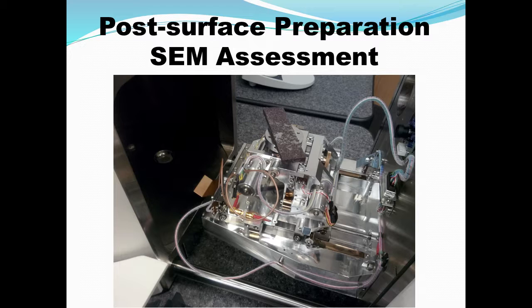I just wanted to say one thing here: time in the scanning electron microscope takes a lot of time, and we can't do 100 samples on every square centimeter of the surface. So what we did on these is the first three, we scanned the entire surface on both sides. What we found was that the distribution of chlorides was consistent. There weren't edge effects. But we took days doing those three. So we went back and just chose three areas on one side of each one, and we would analyze an area on each end and in the middle. And what we had seen from the first three was that was representative of the entire piece of metal.